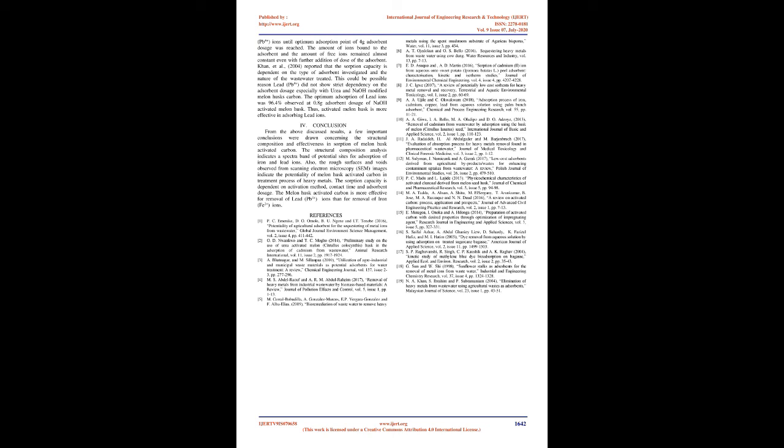Et al, 2004, reported that the sorption capacity is dependent on the type of adsorbent investigated and the nature of the wastewater treated. This could be a possible reason lead, Pb2+, did not show strict dependency on the adsorbent dosage, especially with urea and NaOH modified melon husks carbon. The optimum adsorption of lead ions was 96.4% observed at 0.8 g adsorbent dosage of NaOH activated melon husk. Thus, activated melon husk is more effective in adsorbing lead ions.